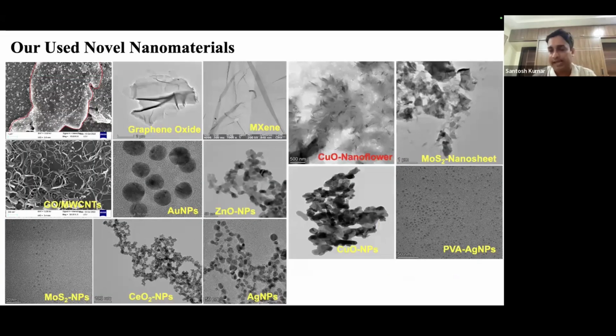So here, apart from the optical fiber, to develop the Waveflex biosensor, we have used several unique nanoparticles. Especially gold nanoparticle, silver nanoparticle, and PVA coated silver nanoparticle to add the localized surface plasmon resonance technique, LSPR technique. And apart from that, graphene oxide, MXene, multi-walled carbon nanotube, molybdenum disulfide nanoparticle, copper oxide nanoflower. These are also unique nanoparticles we have synthesized in our lab.